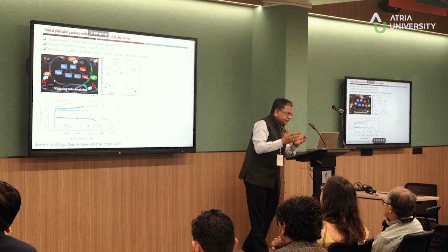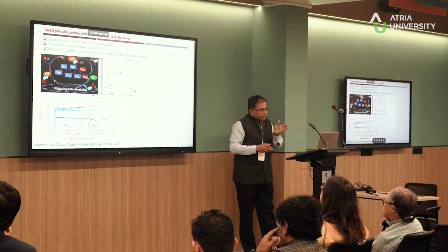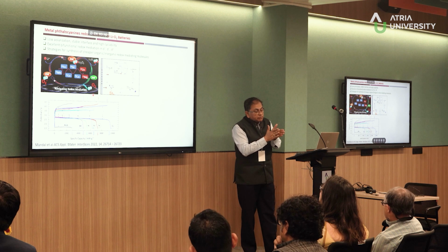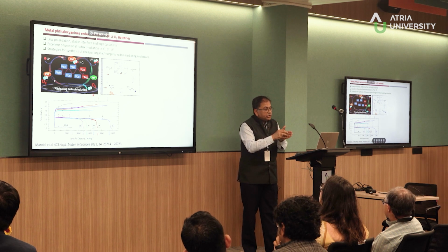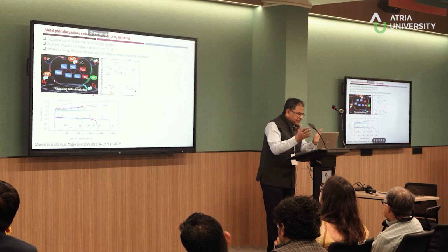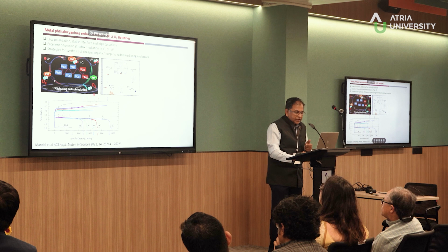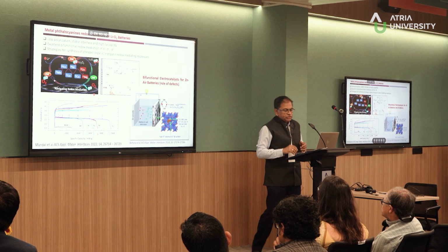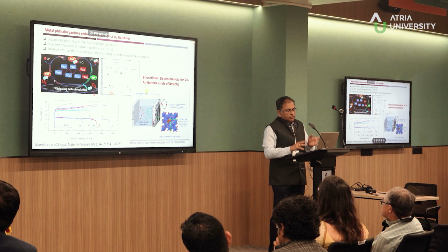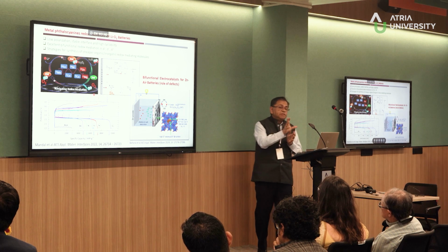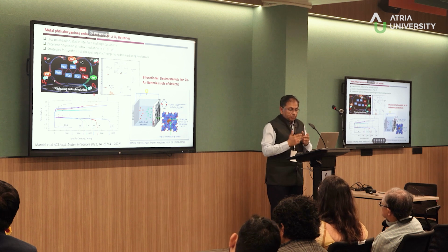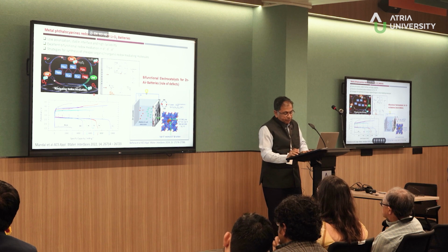So what we have done is we have taken redox mediators. This is a concept which many use in electrochemistry. The advantage of a redox mediator is you're not actually loading onto the cathode gas diffusion layer. It is somewhere very close to the electrode-electrolyte interface. So all your reduction and oxidation is done via the redox mediator, which is in the liquid electrolyte. So this was an exhaustive study. We looked at how the d-shell configuration affects the electrochemistry. In recent times, a student who submitted his thesis designed a bifunctional electrocatalyst. He's now proving the role of defects here. How defects assist bifunctionality and can generate a zinc-air battery.